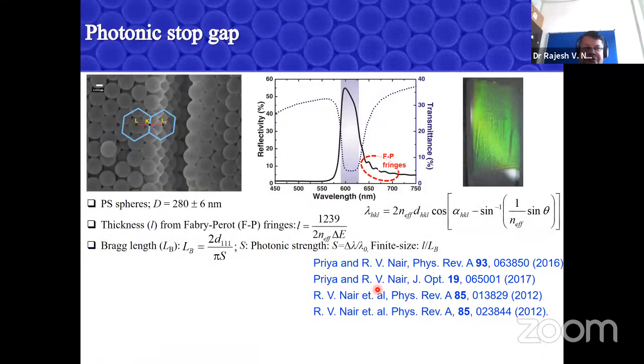So in our lab at IIT Ropar, we made these samples. We buy these microspheres. These are 280 nanometer, 300 nanometer in diameter, 0.3 micron. We have some understanding and some idea how to make it. And our recipe works actually from 200 nanometer to 1.6 micron. So we can make these samples.